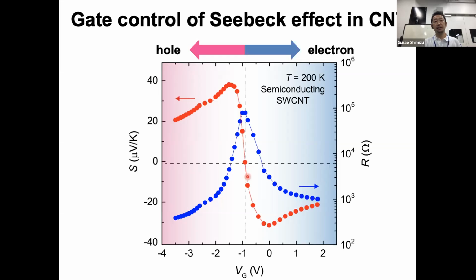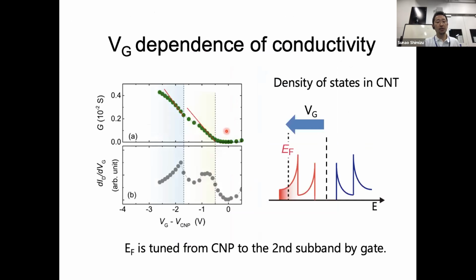So this data clearly shows us that we can control the Fermi energy or carrier density of materials systematically by using the electric double layer gating technique. I want to focus on the gate voltage dependence of physical properties. The upper left figure shows the conductivity of the carbon nanotube thin film as a function of gate voltage. When we reduce the gate voltage, I mean, when we increase the number of hole carriers in the carbon nanotube, we observe the enhancement of conductivity, and also some change of the slope here and here.